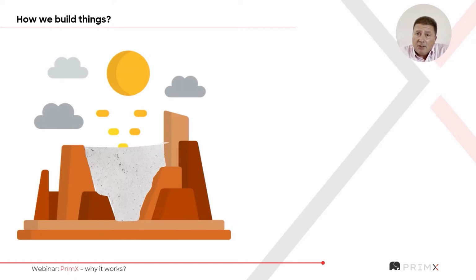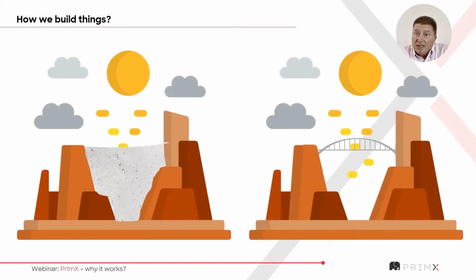However, there is nothing to stop us bridging a gap, if we wish to, with plain concrete. It's just that, as a rule of thumb, whatever the width of the gap is, that width plus a little bit will be the depth of concrete that we use to bridge it. However, if we use steel bar, we can actually start to reduce that section depth of concrete. And if we put that steel bar into tension, then we begin to reduce that section depth even further.